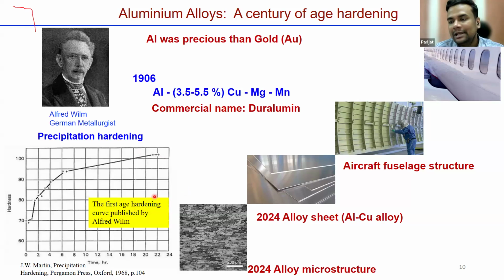After this phenomenon, because earlier aluminum is very ductile, soft, it doesn't have much strength, it did not have any commercial or practical application. But when Alfred first discovered this effect, he found out that yes, aluminum alloy also can be hardened. It is not only ductile; it can strengthen the material. And the strength can be sufficiently high so that we can use that material in our practical uses of daily lives. So after that, the whole aircraft body structure, aircraft fuselage structure, all these are made of aluminum alloy because it's lightweight and simultaneously it gives a high strength. So we have a high specific strength in that kind of aluminum alloy.